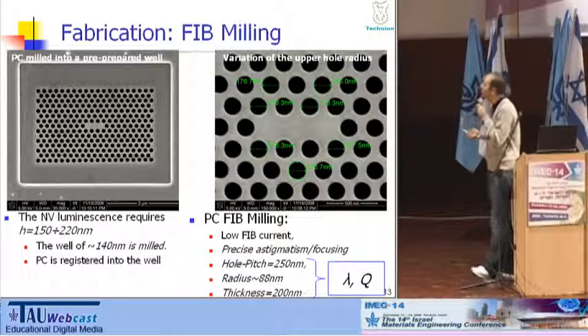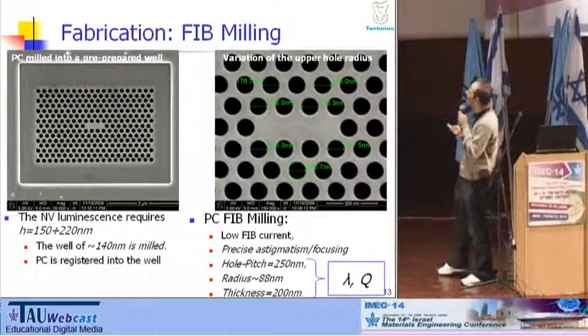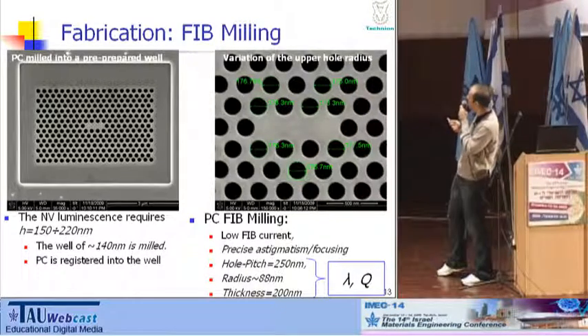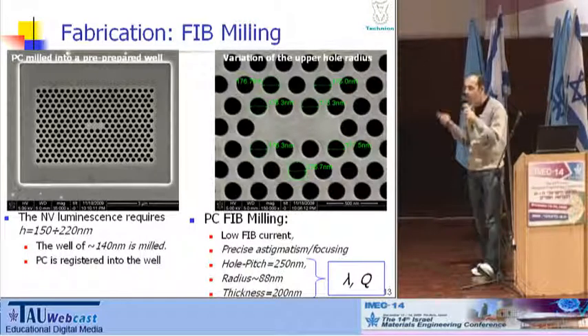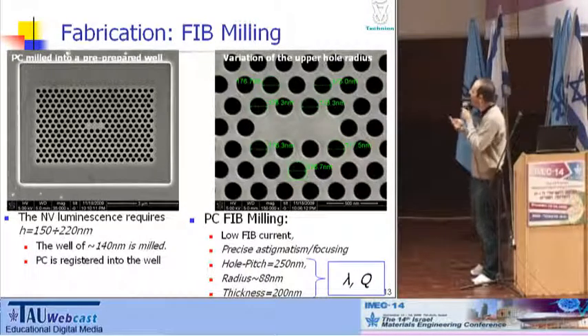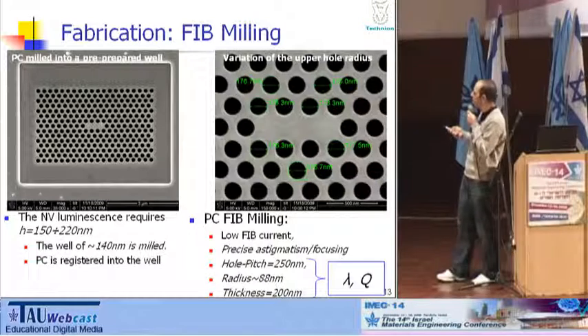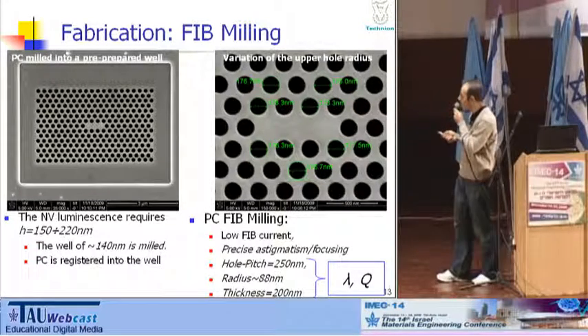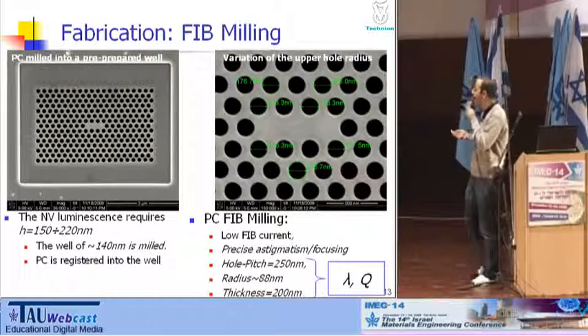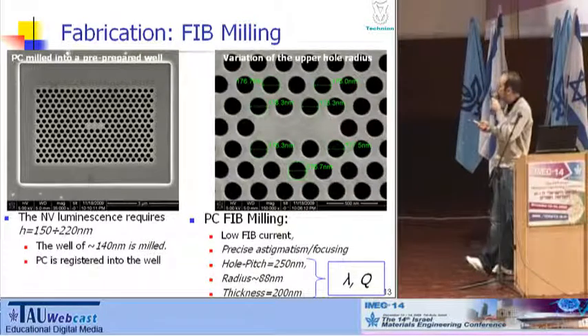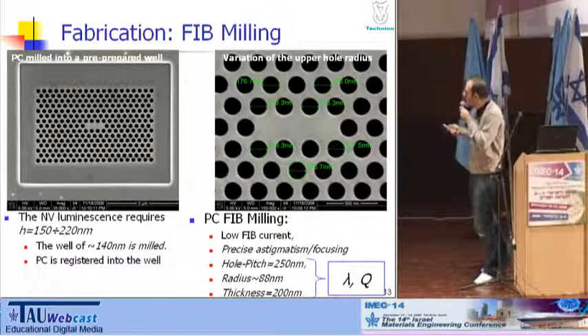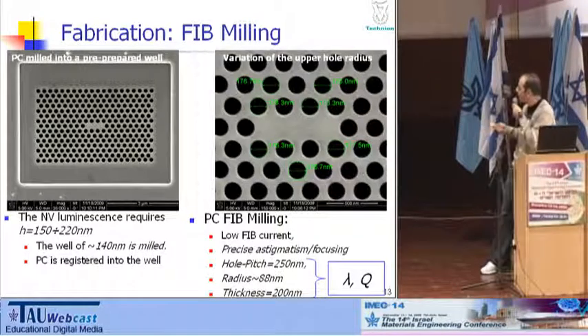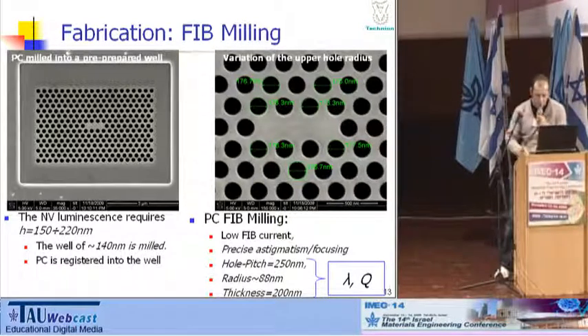You can see here the masterpiece of astigmatism and focusing, because the radii here are very, very uniform on a nanometer level. And generally the pitch is 250 nanometer, the hole radius is 88 nanometer, and the thickness is around 200 nanometer. All these geometry parameters are important since they define the wavelength and the quality factor.